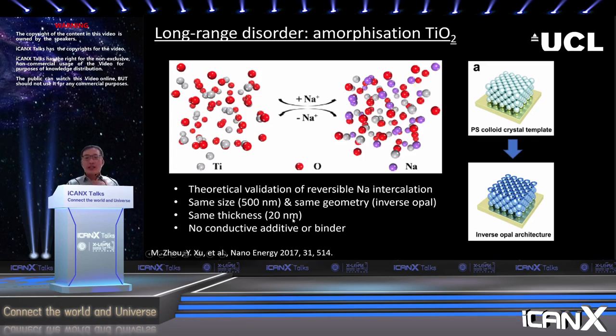And we combined the ALD with the polystyrene colloidal crystal template, where we can obtain electrodes with exactly the same geometry, and the material will not need conductive additive or binder to work as an electrode. So in this way, we're able to exclude the influence from other components in the electrode. Therefore, we can exclusively study the effect of amorphization of the material.